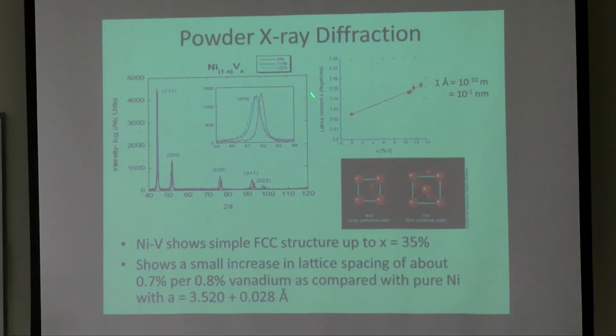And this little picture here takes a look at, let's see, I think it was this one. So the 200 peak would be this. If I were to blow this up, I can see that different samples are not exactly on top of each other. And this gives me an indication of the lattice constant, which is here. So what this graph is saying is that this is pure nickel, and if I add more vanadium to it, so if I'm diluting the alloy, I'm increasing the lattice constant, and so this is an indication of the crystal structure of the material.